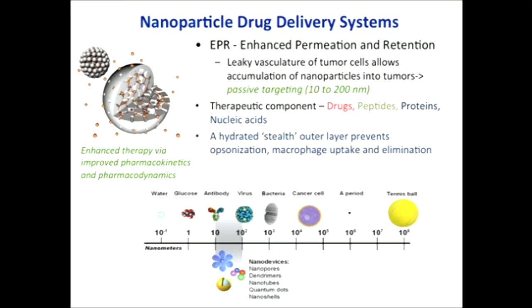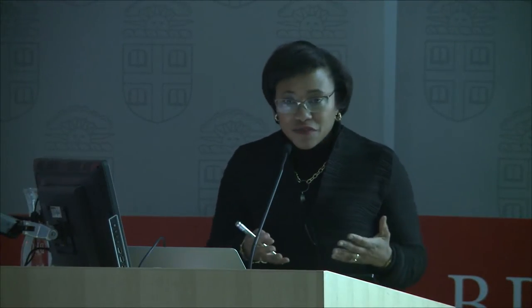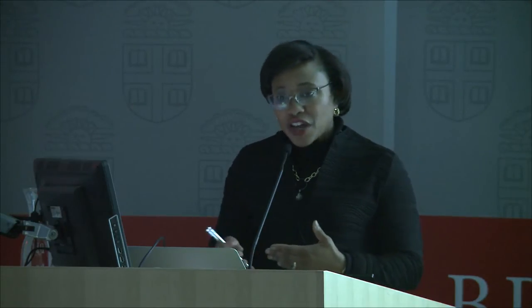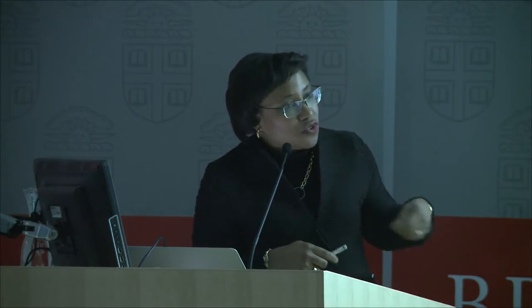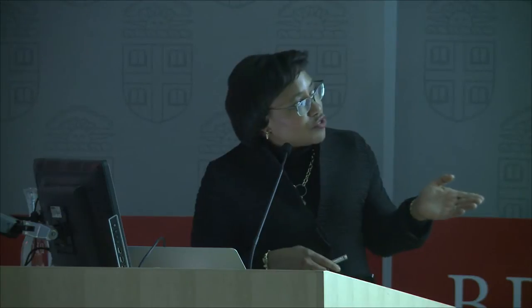We call this the enhanced permeation and retention effect. And we take advantage of the fact that the vasculature is smooth and uniform in the rest of the body, but in these tumor regions, we can actually get nanoparticles to leak out. Now, the passive targeting that this allows means that when we have a nanoparticle that is within the range of a few tens of nanometers, some people believe up to 100, others believe up to 200 nanometers in size, you can get a larger portion of these nanoparticles into the tumor. And that gives you a longer time frame, if that nanoparticle contains a drug, to allow it to release that drug before it gets cleared away. So this is one of the reasons nanoparticles become interesting.